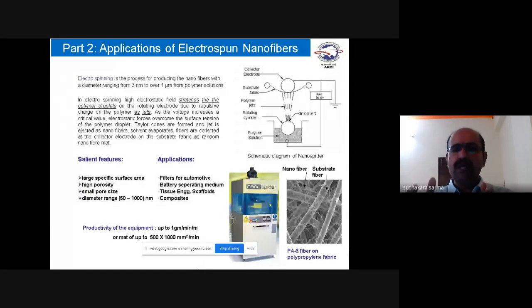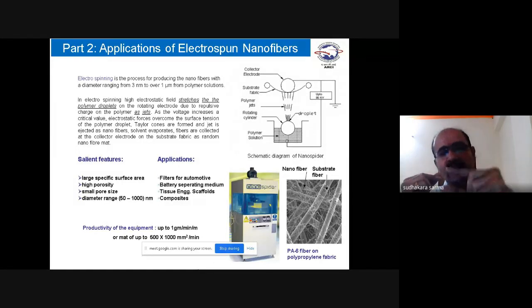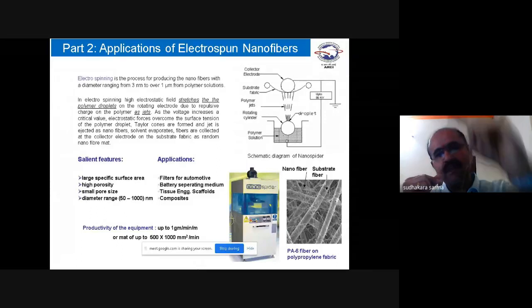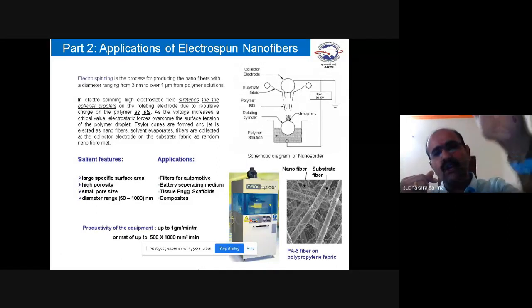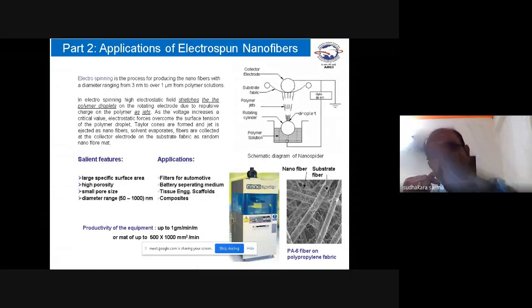We will apply the electrode voltage up to 80 kilovolts. It's a high electric voltage, and when the applied voltage reaches a threshold value of some 45 kV, the polymer solution on the surface of the electrode forms into droplets, and the droplet is charged. Charged particles have repulsion, and due to repulsion, the droplet is ejected as a fiber, and tries to travel to another electrode, ejected as a jet, and at the ground electrode there is a substrate material.